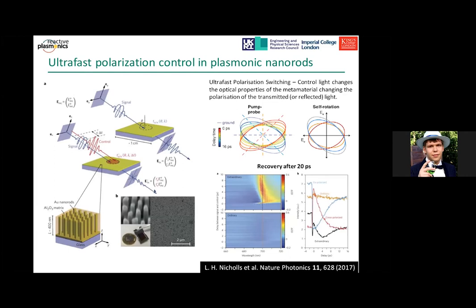For this, we build upon our long expertise in making these scalable, very convenient plasmonic nanorod composites, which are designed to be uniaxial material, in addition to being plasmonic. And because it's uniaxial, excitation of the hot carrier ensembles in the material affects both ordinary and extraordinary refractive index. For example, in this particular case, mostly extraordinary, which allows us to demonstrate the rotation of the probe beam if it's capable of being affected by both extraordinary and ordinary refractive indexes.